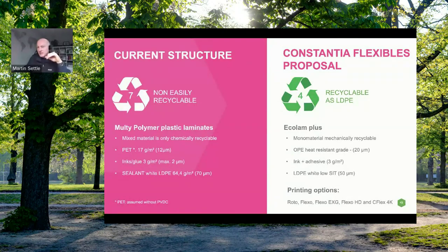But these weren't the only tests we did. As you can see there, this did drive a change in the wrap, flexible laminate material that we used, away from the PET structure, which at best was classified as mixed material, to a mono PE laminate. And it was classified as mono PE, even though we had a barrier in there of up to 5% by weight of EVOH, so acted as an active barrier. It still met all the requirements for recyclability into RecyClass, but it also met all the requirements for OPRL, RAP, C-Flex, APRL, UKPP and USPP. So by default, we designed a multi-use material in a mono PE.